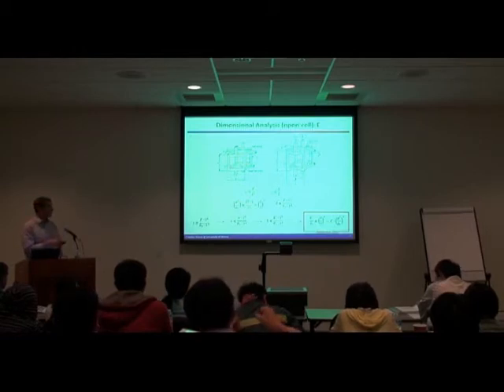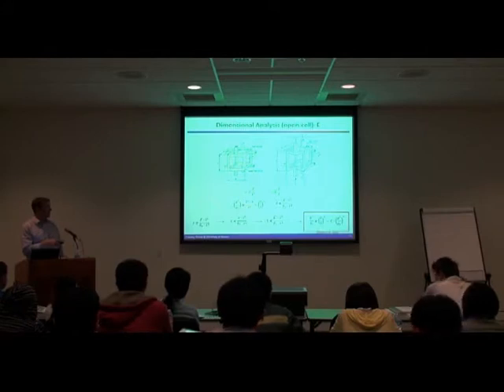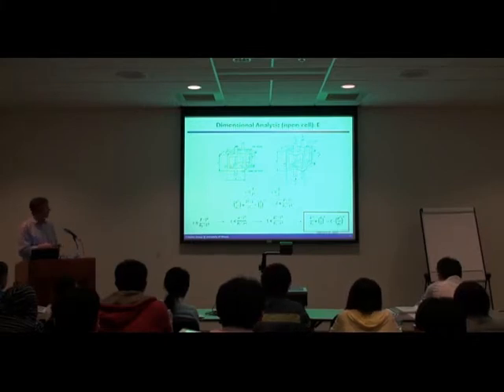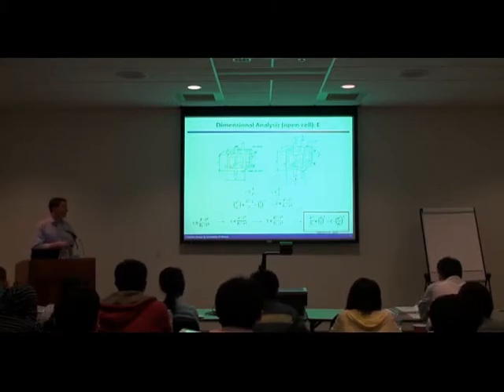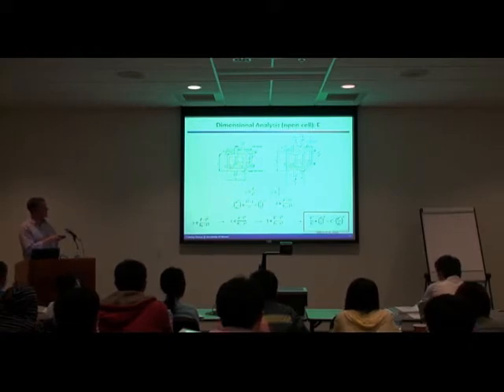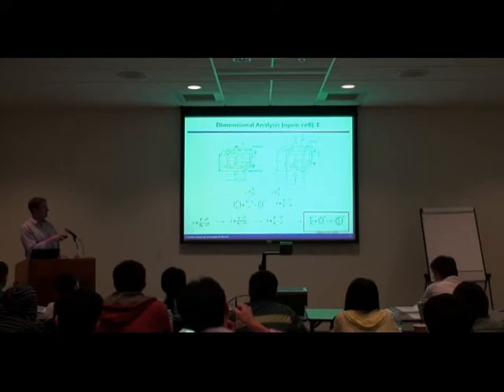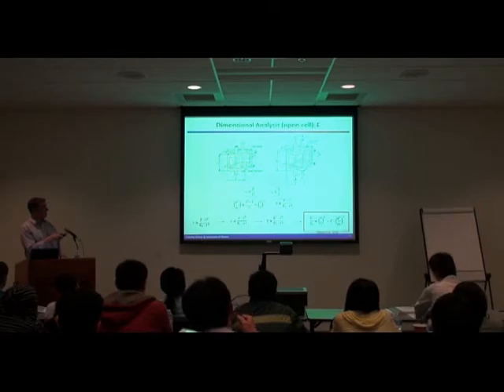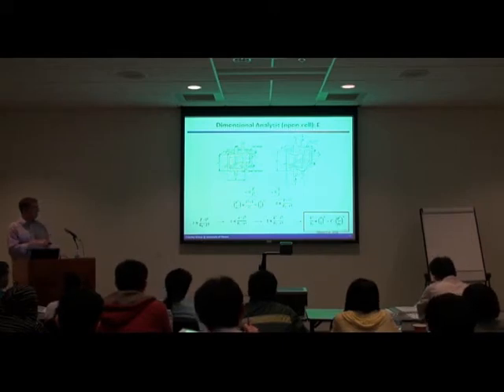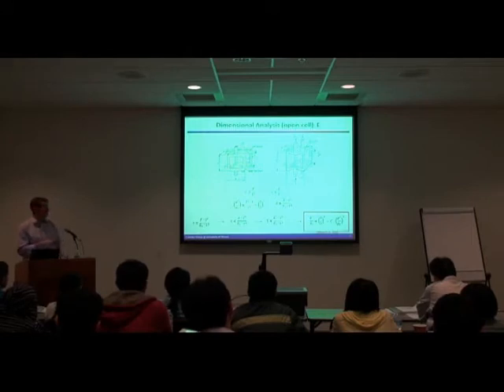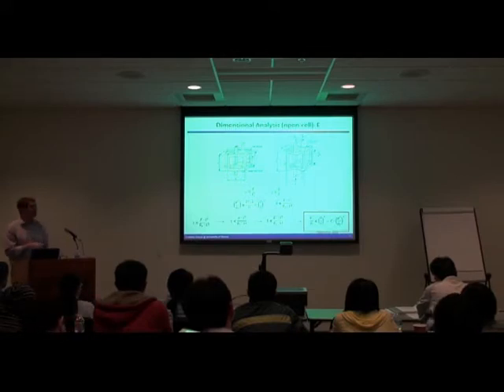And the last feature you need to start to define is this idea of relative density, which we're going to talk a lot about in the course of the rest of the lecture. The idea behind relative density is that this is a measure of how much solid is in the material. So if you think about calculating a relative density for this square unit cell, what you would do is take the total volume of material, which would go as length times thickness squared times some constant, and divide it by the total volume of this unit cell, which would be a length cubed sort of relationship. And so that gives you a relationship. Again, this is not a direct relationship, but it's a proportionality that the relative density of material is proportional to the ratio of thickness to length of the individual fibers that describe the material.